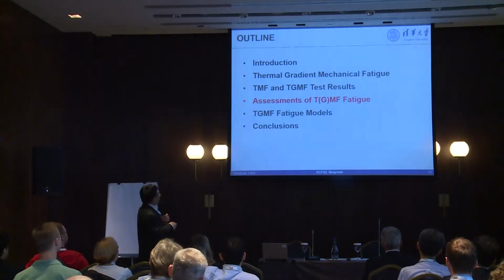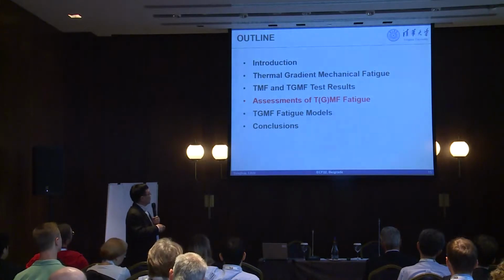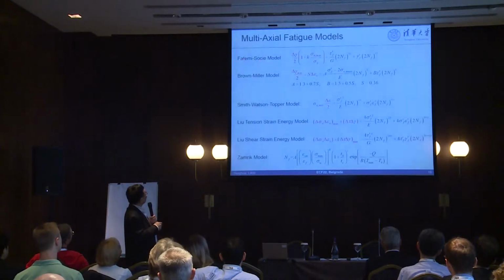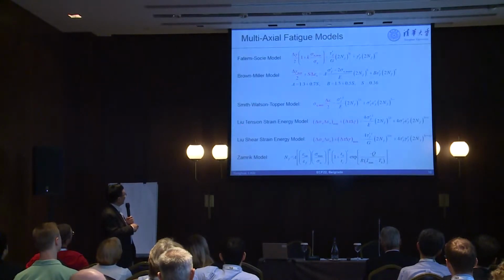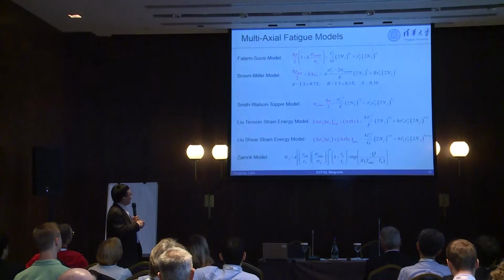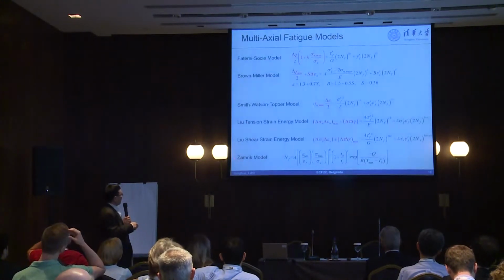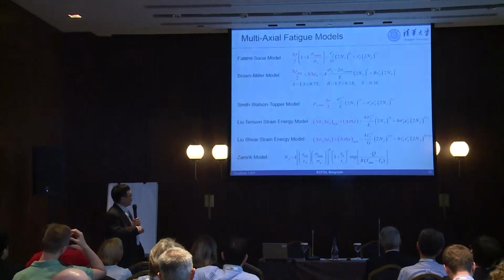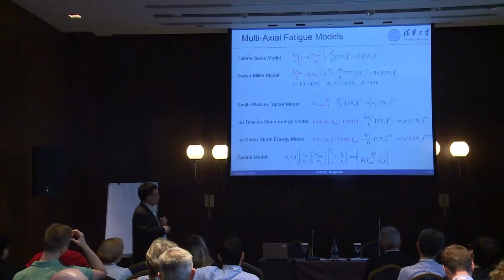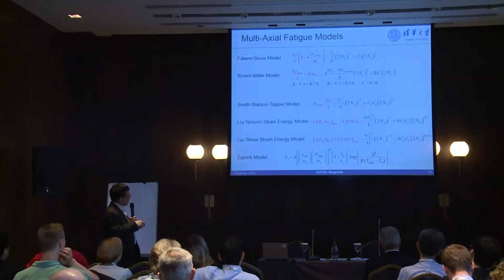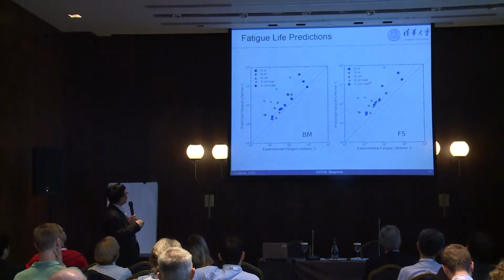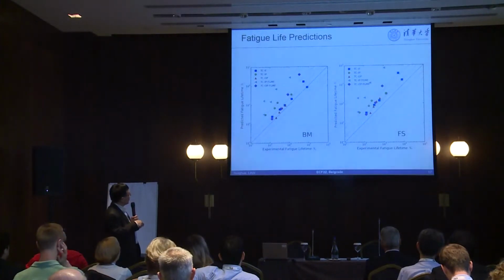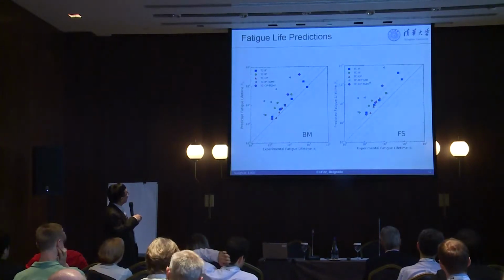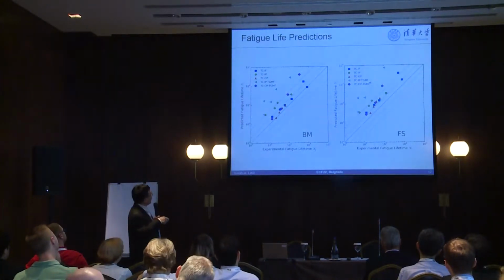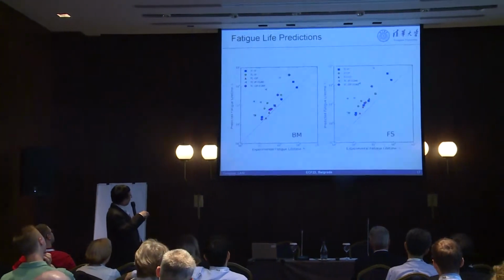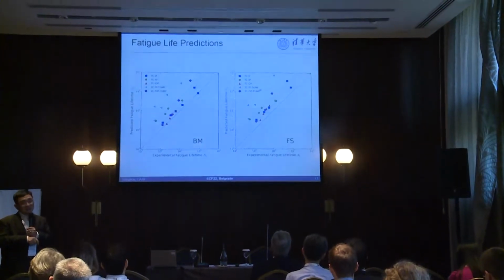Okay, now we are going to see. We use at first different multiaxial fatigue models to test. We chose several: Fatemi-Socie, Brown-Miller, Smith-Watson-Topper, and 2 different Liu models. Liu is where we introduced the energy model, a rather new model. The Zamrik model was specially developed for TMF 3 years ago. And we test all of them. I will show you quickly the comparison of the different models with the experimental results. Here you see the experimental results. Here you see the prediction based on different models, from Brown-Miller, Fatemi-Socie. You see all results are always in this region. That means predictions based on these models are not conservative at all.